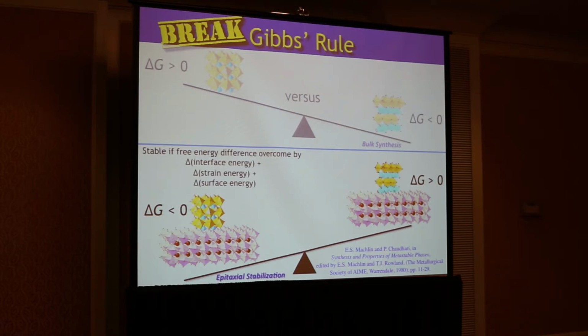You want to use a material that is isostructural to the polymorph that you want, the polymorph that was metastable. So the additional terms that come up in looking at the free energy here are the interfacial energy, the strain energy. So you want this material that has the same motif to also be well lattice matched. And the surface energy of this entire system compared to this entire system. So this is epitaxial stabilization. And this is a great example of breaking the rules.